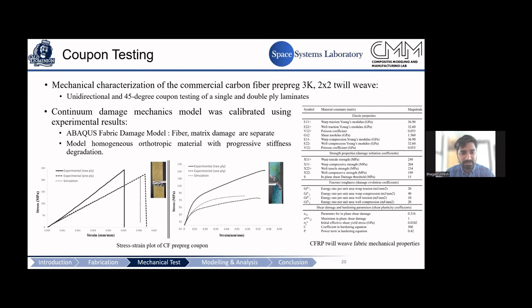An important finding is that we tested with two plies and one ply. The two-ply configuration has better performance than the one-ply, even though it's the same material. When going from a thicker to a thinner structure, the material properties change. This is why the failure mechanics of a stiff structure cannot simply be applied to a thin structure — demonstrating the significant importance of calibrated computational models for thin-wall composites.